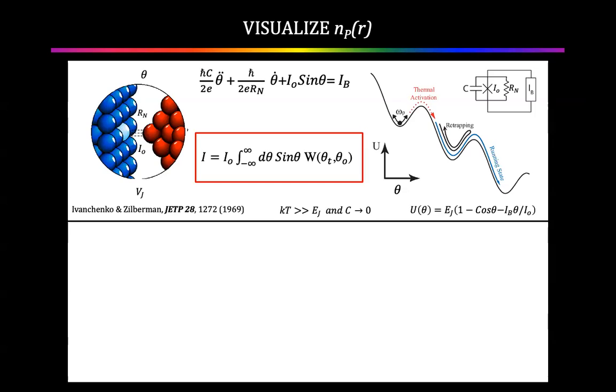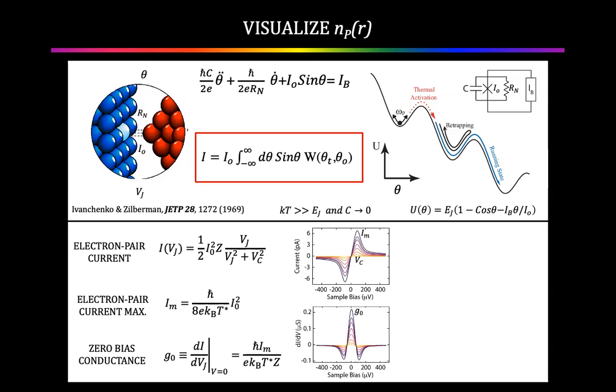So that problem was solved by Ivanchenko and Zil'berman in 1969. I love this paper. It's a beautiful, elegant paper. In the limit where the capacitance goes to zero, you can solve this equation as a Langevin equation, very nice solution. And they show that the pair current at finite voltage has this form. Okay, this form. And the maximum in the pair current at finite voltage is proportional to the Josephson critical current squared. Or if you want to measure pair conductance, dI_pair/dV, there's a peak in the pair conductance. The peak in the pair conductance at zero bias, which has nothing to do with any Majoranas, just the Josephson effect. The peak in the conductance is proportional to the maximum, which is proportional to the Josephson critical current squared.